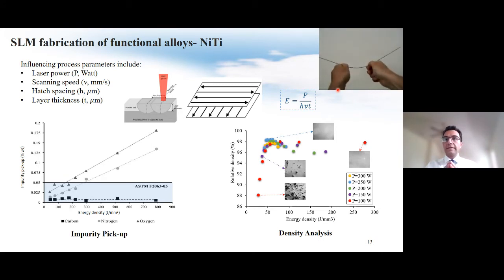Very close to the stainless steel. Well, let me talk about the most important parameters in the optimization that have to be tuned during the procedure of the optimization. These parameters for additive manufacturing or SLMs include laser power, which is the power of the laser, scanning speed, which is the speed of the laser beam travel during the fabrication, hatch spacing, which is the distance between neighboring laser tracks, and layer thickness.